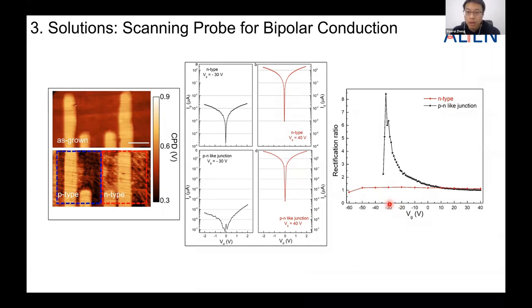So there's only one point where the tip-induced p-n doping dominates the junction. So that's the position here. Once we increase the backgating to a large n-doping, the junction will disappear because the universal doping dominates the channel. Then you would have a symmetric IV curve eventually. So if you look at this IV curve here, at a small negative backgating, the tip-induced doping dominates, and you get a rectifying IV curve. But once we have a large backgating, this IV curve turns back to symmetric.